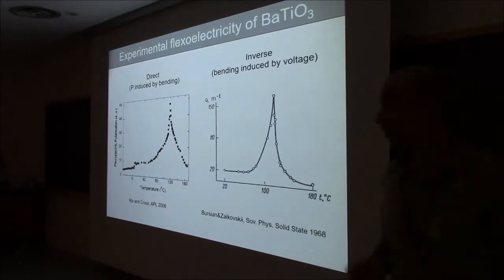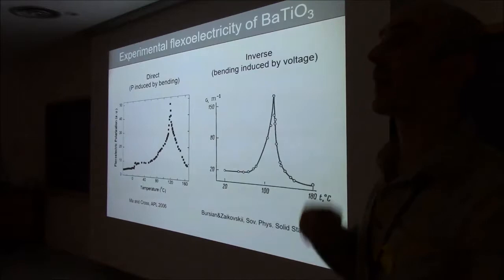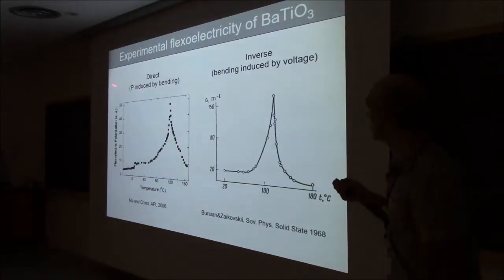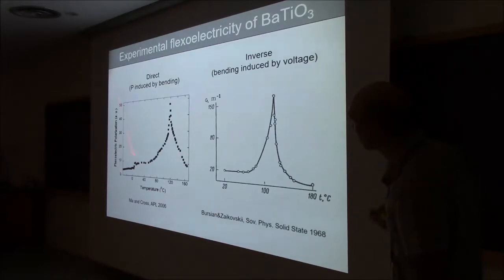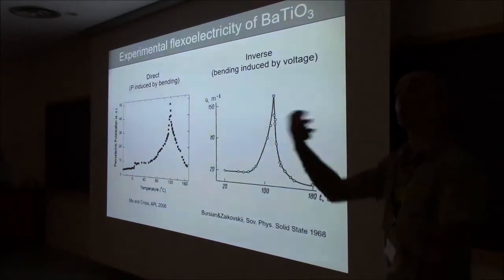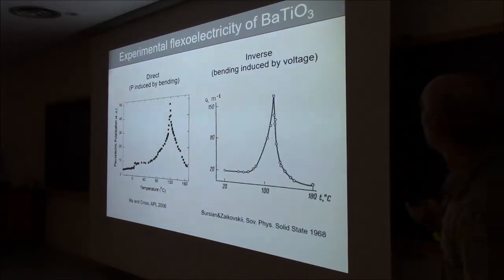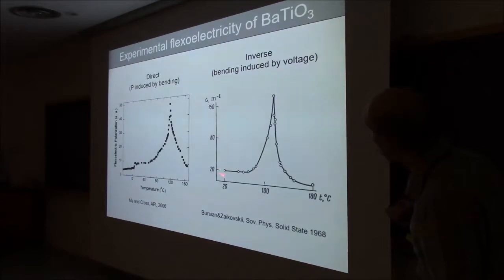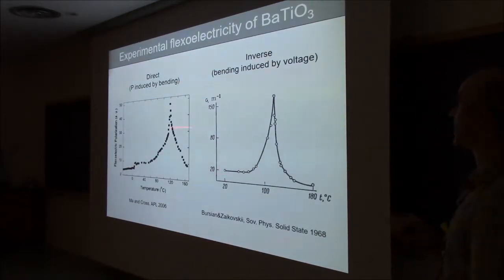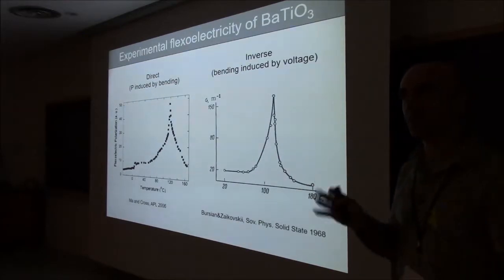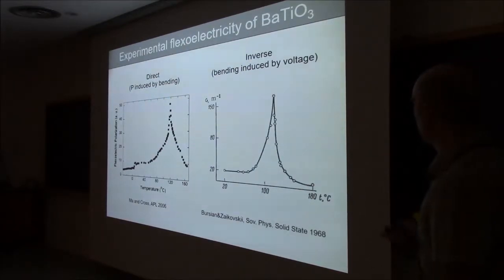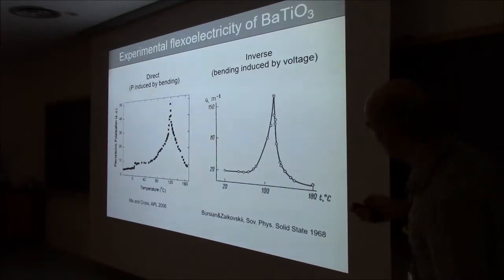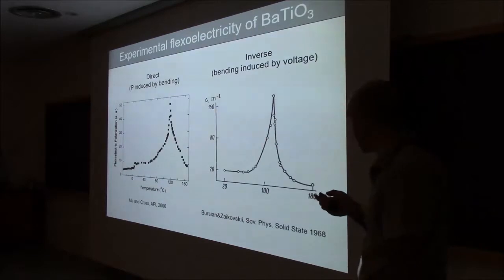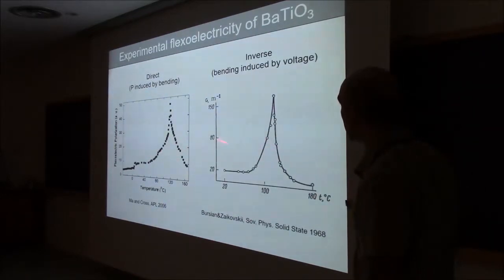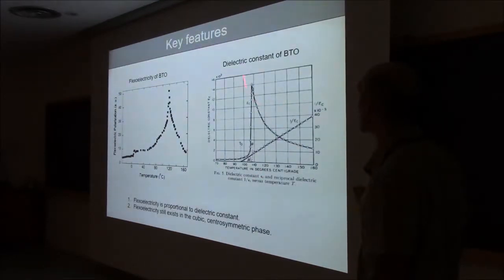Okay. And so, if you take, for example, barium titanate and try to measure its flexoelectricity, you can do so by the direct method. You bend it and you measure the polarization induced by the bending. Or you can do the inverse experiment, the one that historically was done earlier. You apply a voltage, you measure the bending, and you see the bending as a function of applied voltage. And you can see that the two things look exactly the same, which is reassuring. And you can see a couple more notable features. You're probably familiar with the dielectric constant of barium titanate, and if you are, you will see immediately that the shape of the flexoelectric coefficient looks exactly the same as the shape of the dielectric constant. Okay?